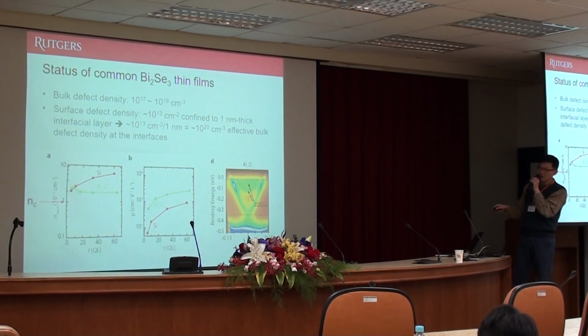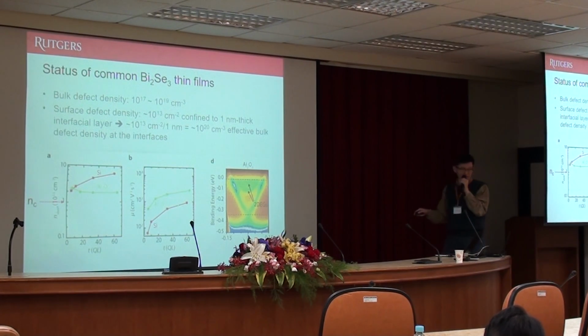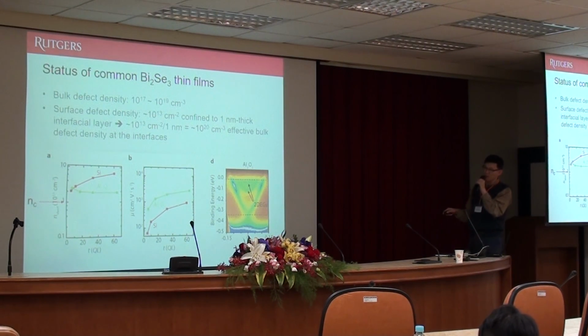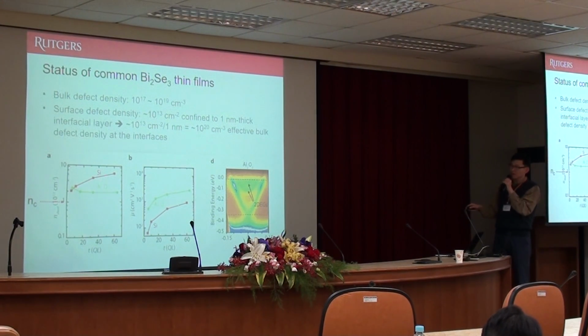Earlier I mentioned that our target carrier density is 10 to the 13. This is our target value. So carrier density should be below 10 to the 13 in order to have any hope of making them bulk insulating. As you can see, on any substrate, on silicon, aluminum oxide, people have tried this and that. You always have more than 10 to the 13 carriers. So your bulk is actually always metallic. So this line is so difficult to achieve, so difficult to go below this. That was the target value.